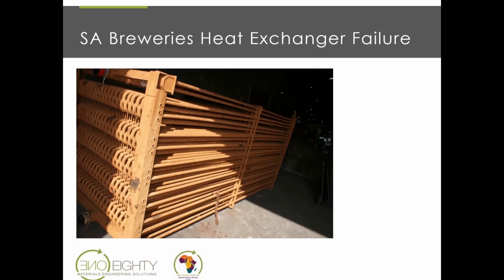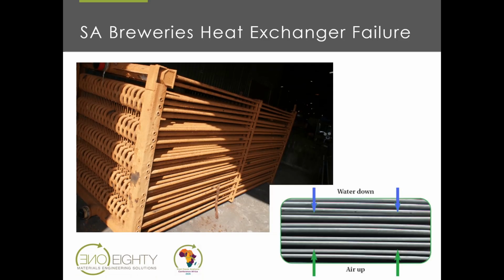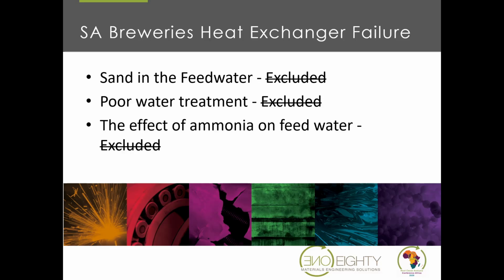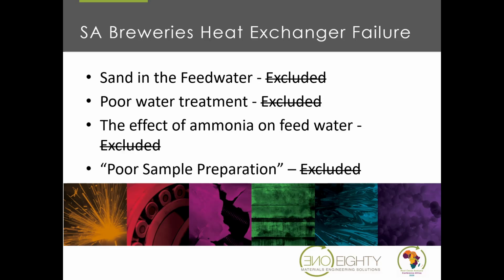So we went back to the galvanizing, and after shutting down almost every single counter argument, the sand in the feed water was excluded, water treatment was excluded, the effect of ammonia on the feed water was excluded, and as for sample preparation, the claim that the features I observed in the prepared samples were attributed to the sample preparation itself was also not reasonable, because there are standards on how to prepare samples with coatings and failed coatings, which we follow, as an accredited lab.